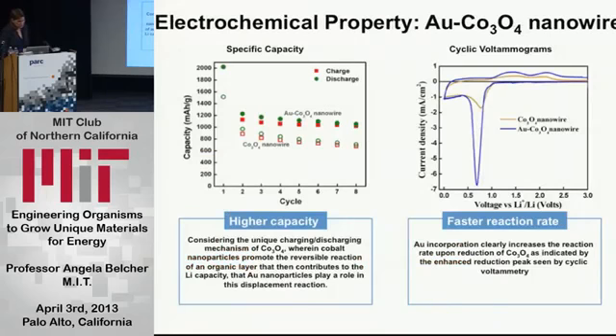And so then you test that as a battery electrode material, and this is capacity versus cycle again. And this is a first generation battery electrode material, and this is the second generation battery electrode material. So it definitely gets better. And we were pretty excited about this at the time when we published in Science, because it was a very, very different idea, and this was in 2006.